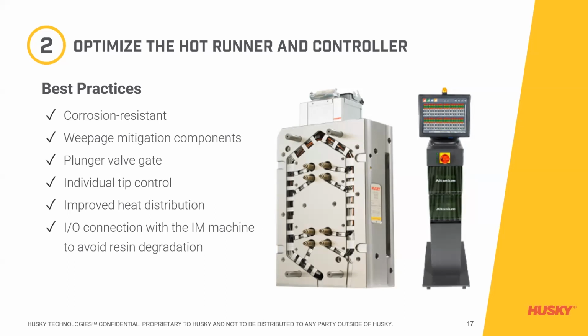The type of gate, so a plunger gate that will give us the best possible gate quality. Individual tip control, improve heat distribution. Basically, we want the best possible thermal profile on that manifold so we don't have hot spots or cold spots that can lead to resin degradation. And an IO connection with the machine to avoid resin degradation. Basically, what that means is that we would recommend a controller that can interface with the machine so that if the machine goes down for a certain period of time, let's say 15 minutes, that controller can automatically bank the heats so that we're not degrading the resin.